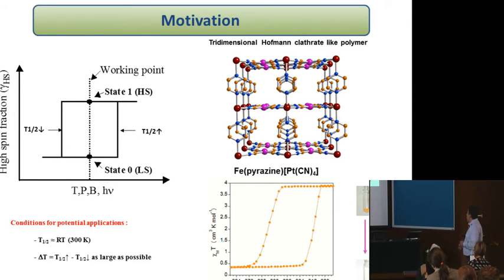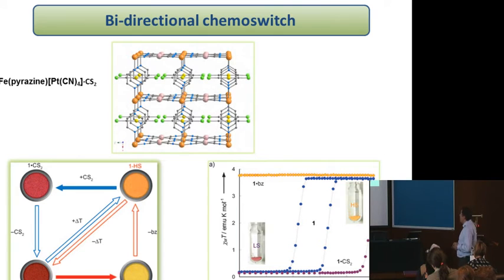Real and Kitagawa also observed that this kind of material is sensitive to the inclusion of guest molecules. Here, for example, we can see the inclusion of CS2 molecules in the packing of these three-dimensional systems. And they have demonstrated a bidirectional chemoswitch. This means that here in blue you have the empty complex, and if you are in the low spin state here, with the red color, and you expose the sample to benzene, you will have a switch of the sample from the red to the yellow color. So we can follow, just by optics, the inclusion of benzene molecules in these materials at room temperature.